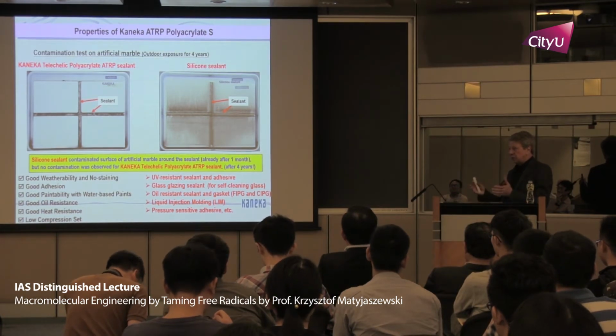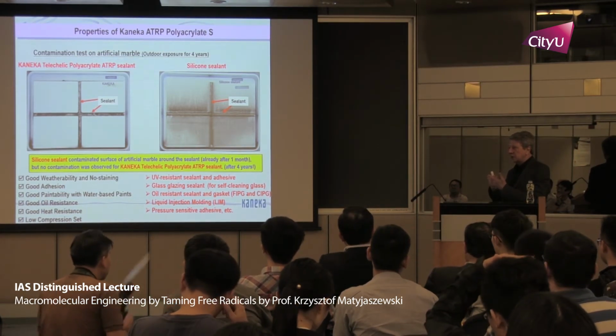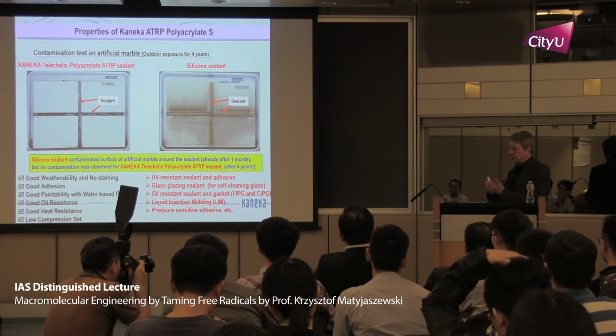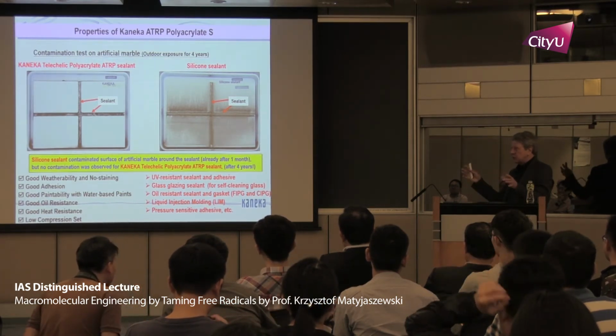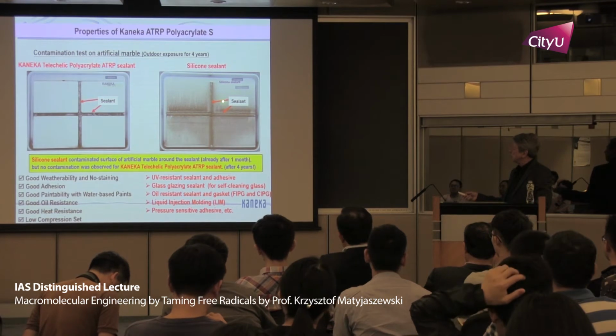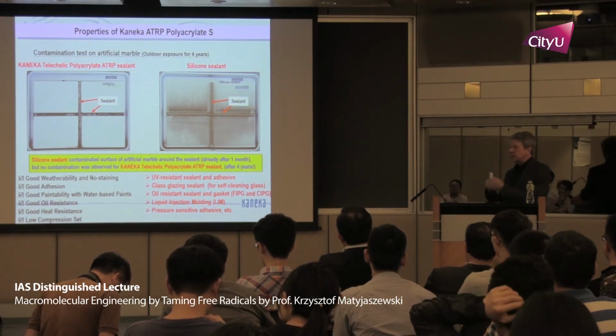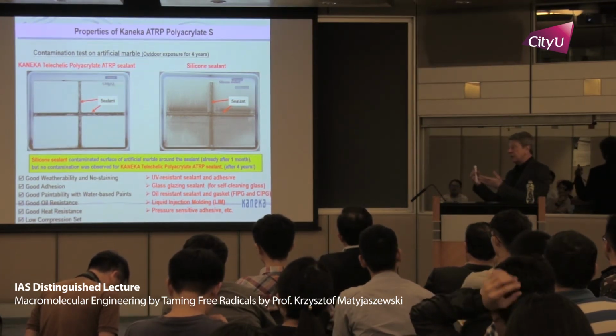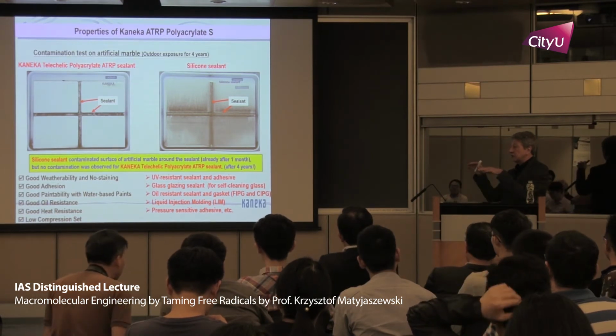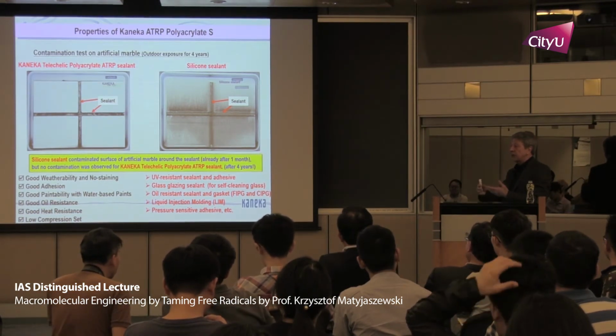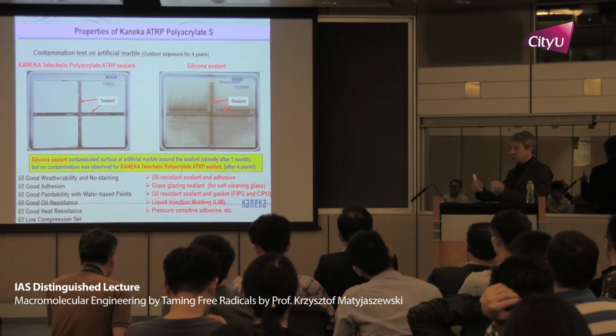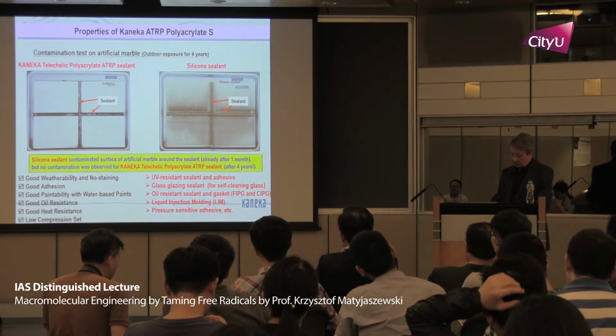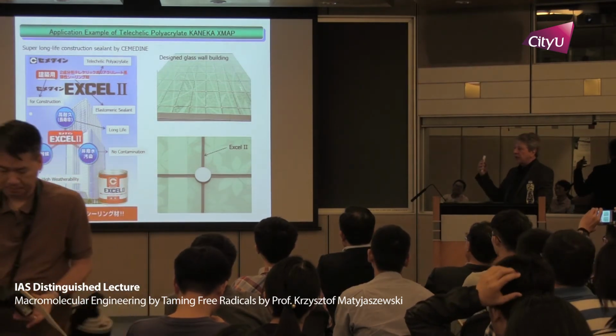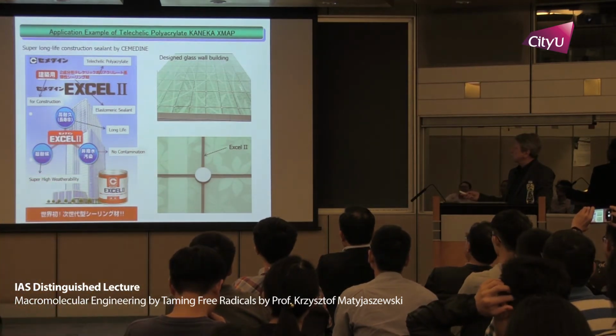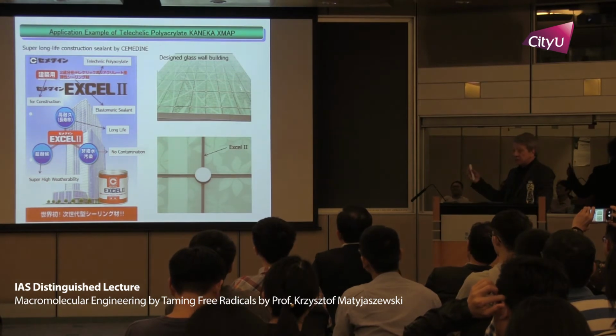First, acrylate is polar, so it interacts with the mineral surface much better than non-polar PDMS. Much better functionality, and there is also leaching, because silicone is a kind of self-healing system, but also a self-leaching system. It is more dynamic, and polybutyl acrylate, once cured, stays like that nearly forever. I think in Hong Kong there are many high-rise buildings, so probably they are using these special sealants also.